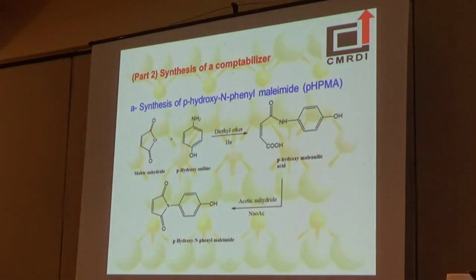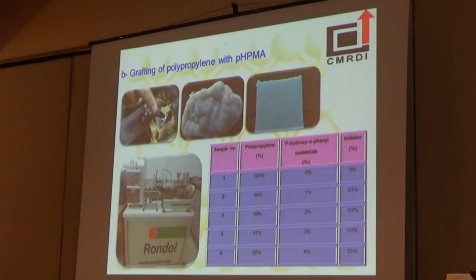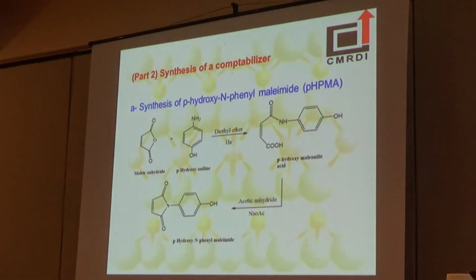The second part of my experimental work is the synthesis of a compatibilizer, which contains both a hydrophilic part and a hydrophobic part to increase the compatibility between the polymer and the layer silicate. At first, we have to synthesize a p-hydroxy-N-phenyl maleimide monomer according to the following equation.